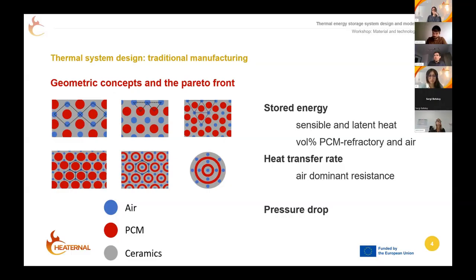The bottom two of those are something I think everyone who does heat exchanger design knows. You have heat transfer rate and pressure drop. You want a high heat transfer rate and a low pressure drop, but usually if you increase heat transfer rate, you also increase pressure drop. So there's a trade-off between those two. Important in this case is that the dominant thermal resistance will be your air compared to the thermal resistance of your ceramics and your PCM.